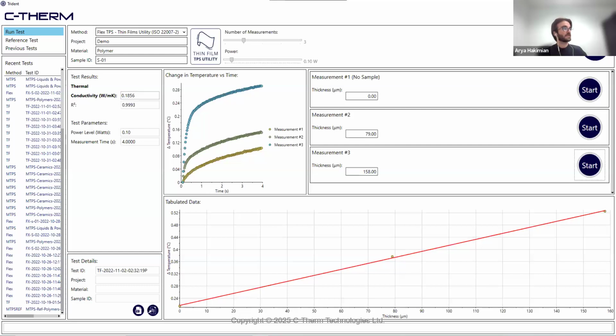This is just a little screenshot of an example polymer thin film that was tested. You can see what the data looks like. This is a snapshot from the Trident software, and you can see the general idea in the process here. Essentially, in the bottom graph, we are taking a measurement of the change in temperature as a function of film thickness, of material thickness. By building out this correlation, assessing a good linear structure within the sample, this is how we go about quantifying or validating the measurement. But essentially, it's a three-part test. Start with your control, one layer of film, two layers of film, and we're looking to assess the linearity between those points.